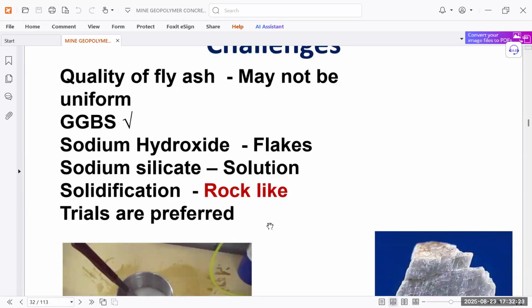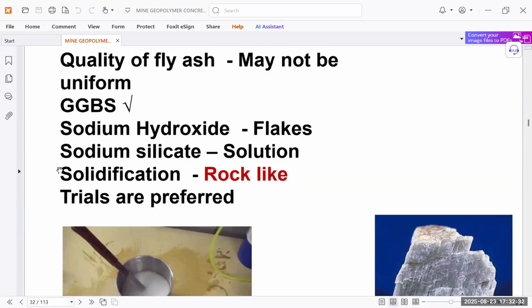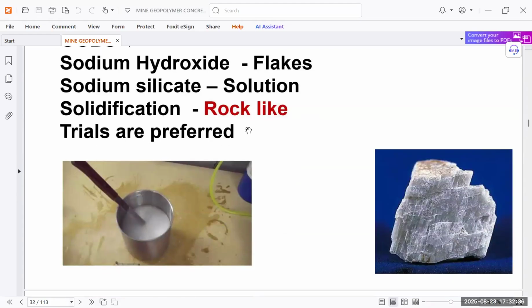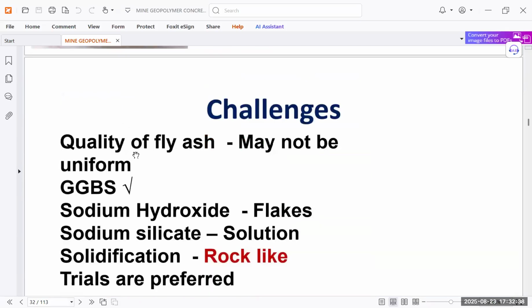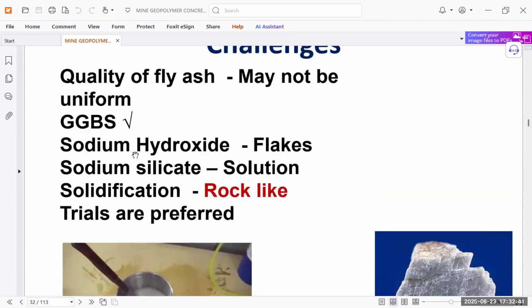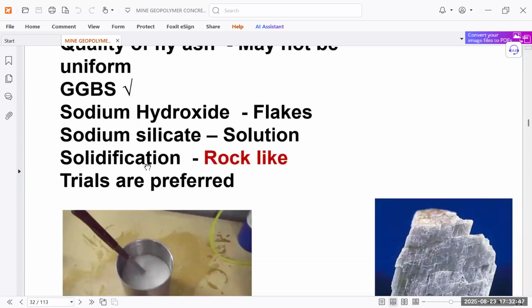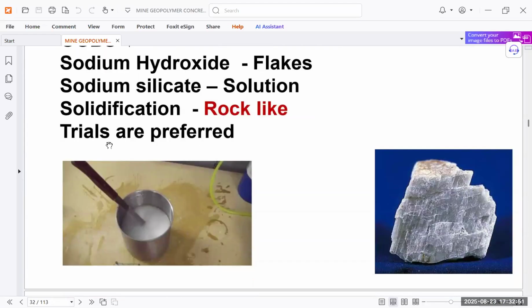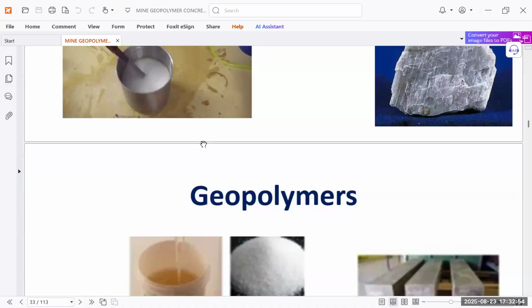The quality of fly ash where you are using it may not be uniform, and GGBS also, and sodium hydroxide may have some flakes. The sodium silicate solution we have to make properly, and solidification also occurs rock-like, and trials are preferred. That is why these are the challenges which we have to see. The quality of fly ash may not be uniform, GGBS and sodium hydroxide flakes are there, sodium silicate solution making is also a challenge, and rock-like solidification is also there. And trials are preferred before finalizing the solution.